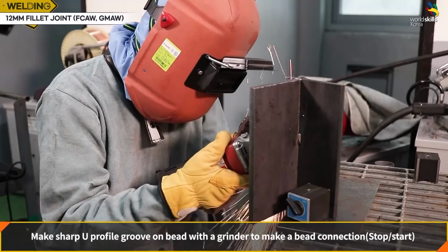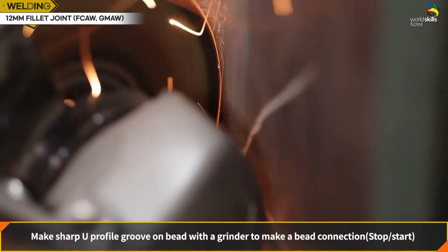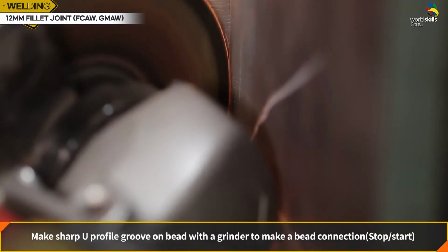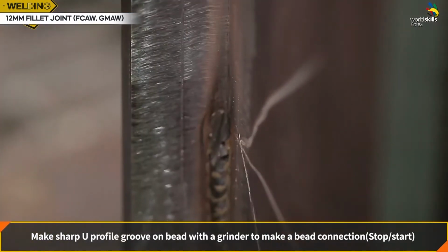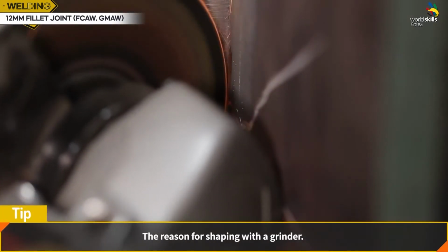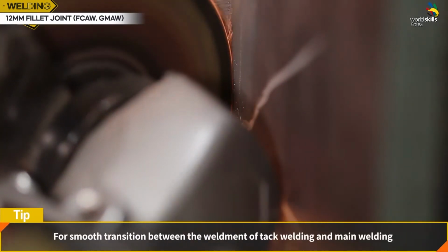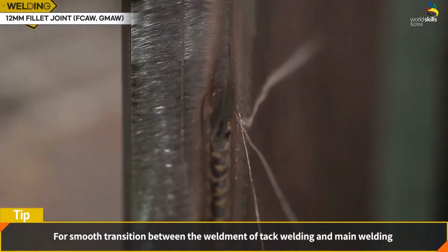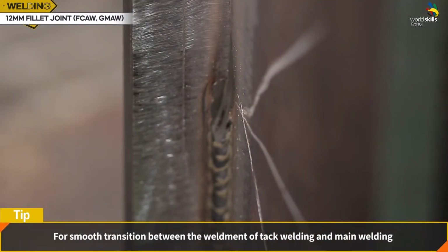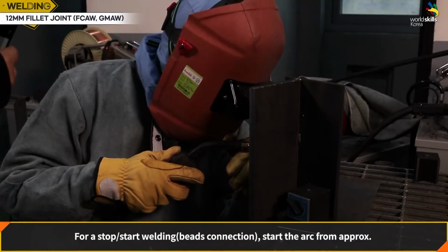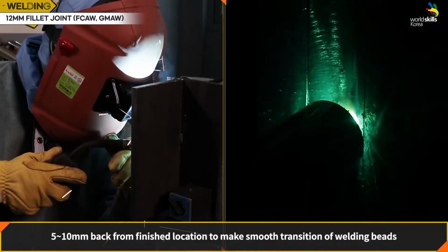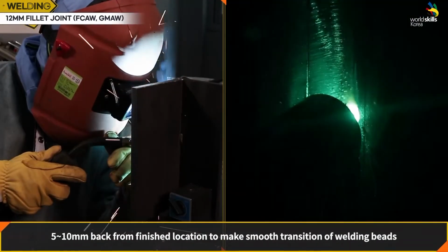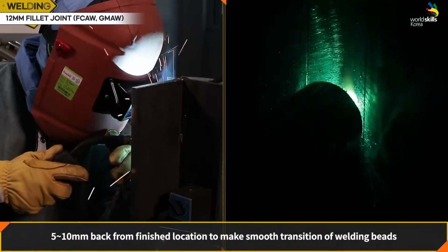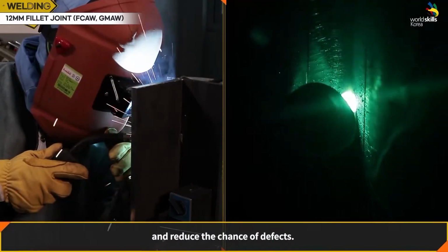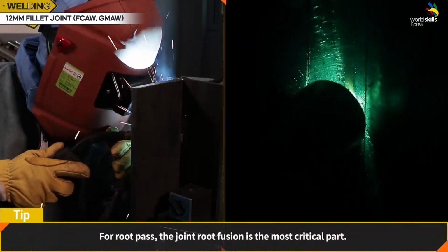Make a sharp U-profile groove on the bead with a grinder to make a bead connection, stop-start. The reason for shaping with a grinder is for a smooth transition between the weldment of tack welding and main welding. For a stop-start welding bead connection, start the arc from approximately 5 to 10 millimeters back from the finished location to make a smooth transition of welding beads and reduce the chance of defects.